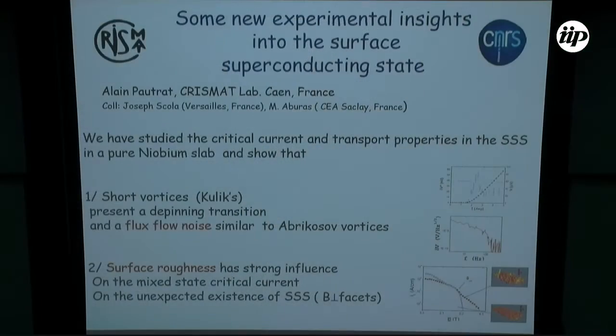Also, normally surface superconductivity is expected when you have a magnetic field parallel to the large surface of the sample. In fact, experimentally, we see surface superconductivity even in the perpendicular geometry. Here we have demonstrated that this is due to small-scale surface roughness and that this surface superconductivity can be completely tuned by a proper surface treatment. I will be happy to discuss this result with you. Okay.